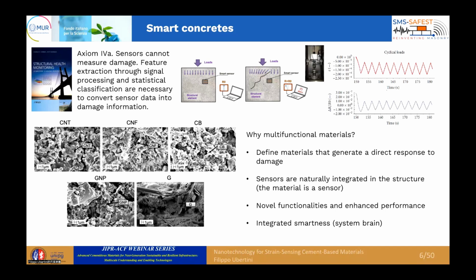So to give you an idea of how well a material like this works, I'm showing you here an experiment on a small cube of smart concrete fabricated in our lab, where in red you see the applied strain with a compressive machine, and in blue you see the electrical signal outputted by the material. You clearly see that there is a very good correlation between the two.